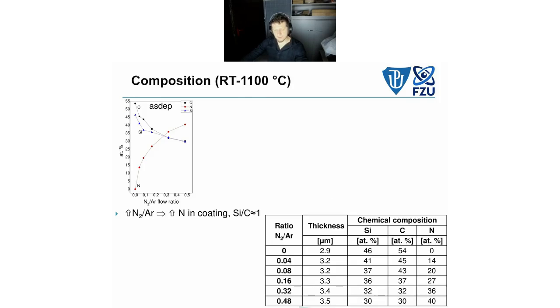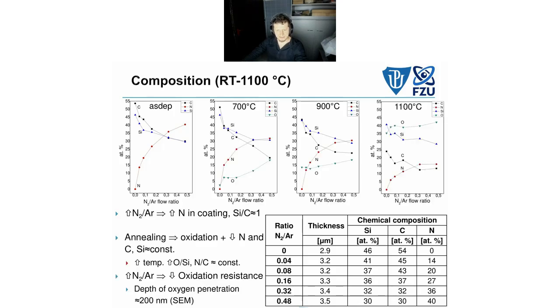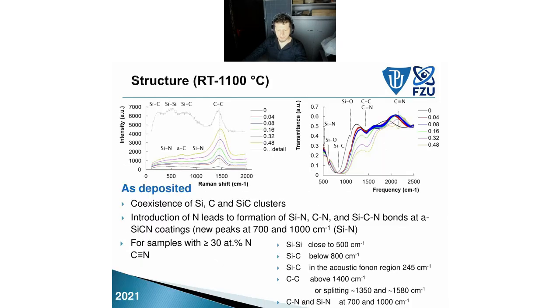Composition. Different ratios give rise to different compositions. As you can see, we have something like a 1:1 silicon and carbon composition, and increasing the nitrogen to argon ratio increases the nitrogen content. After the annealing, oxygen increased. So apparently we have oxidation here, and nitrogen decreased, and carbon also decreased a little. So we have strong oxygen penetration into the material and creation of an oxidation layer, something like 100 to 200 nanometers thick.